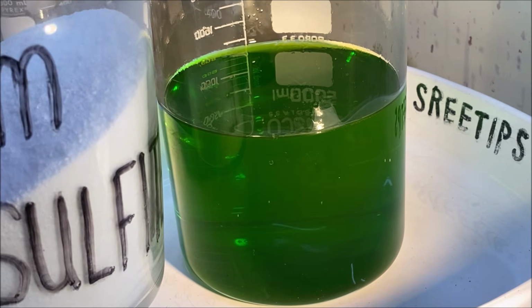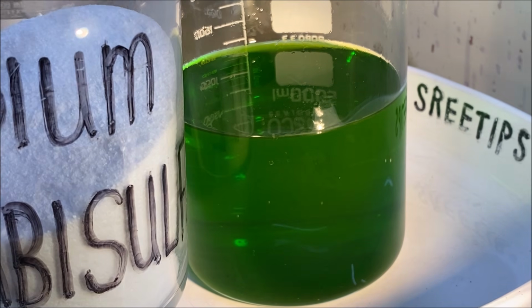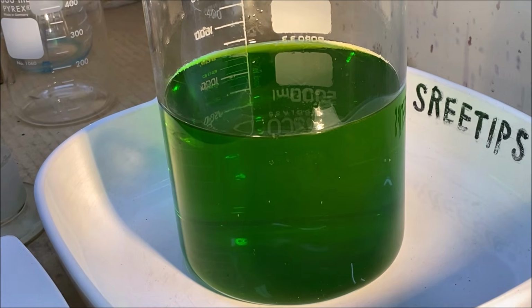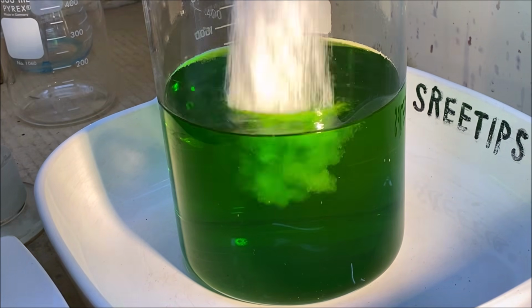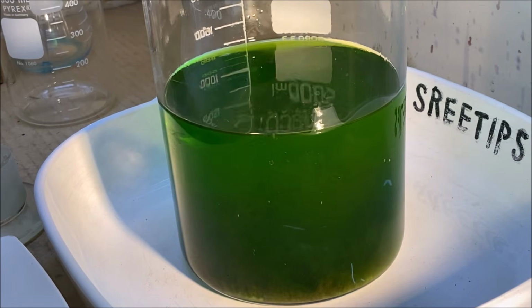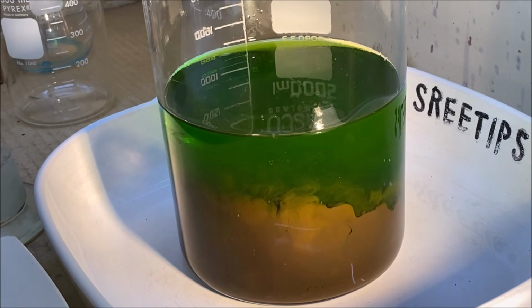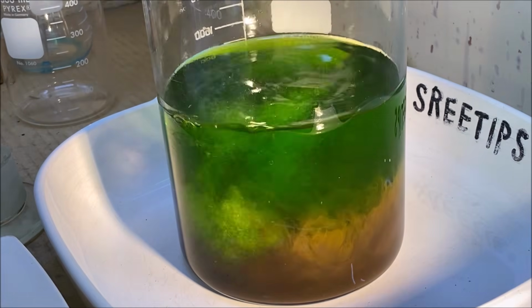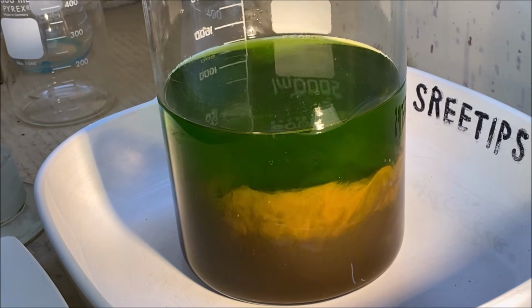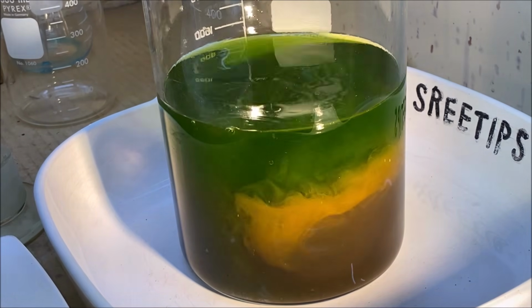Precipitate gold with some sodium metabisulfite. Get it out of this green liquid. I'm expecting 12 to 15 grams of pure gold, so it should only take about 2 or 3 spoons of SMP.